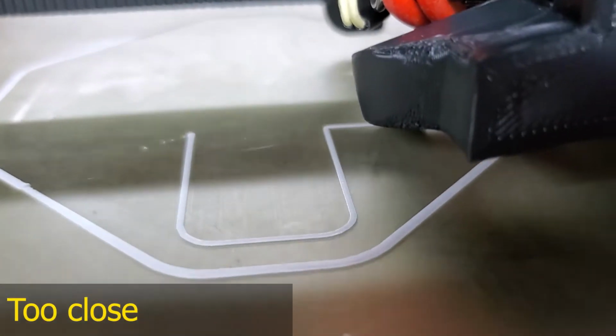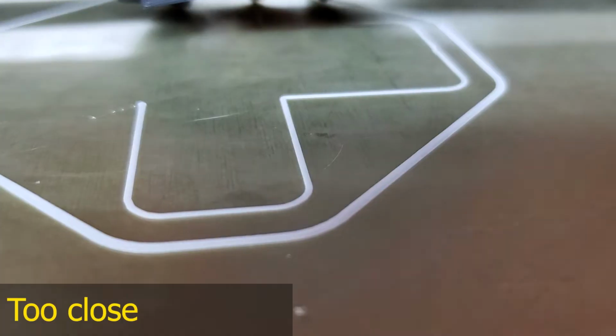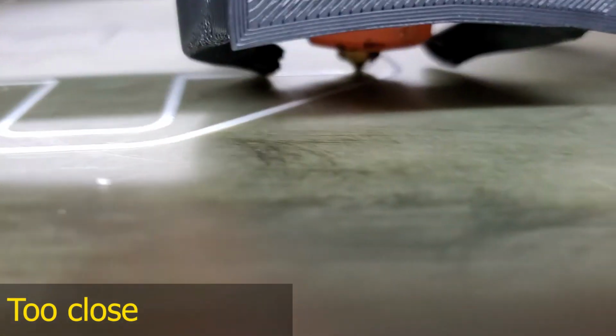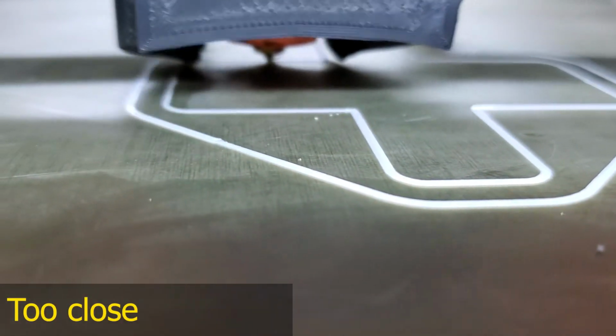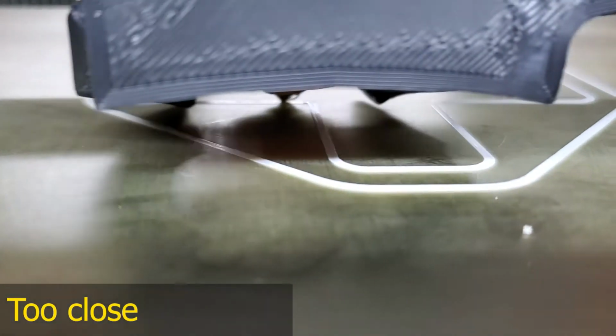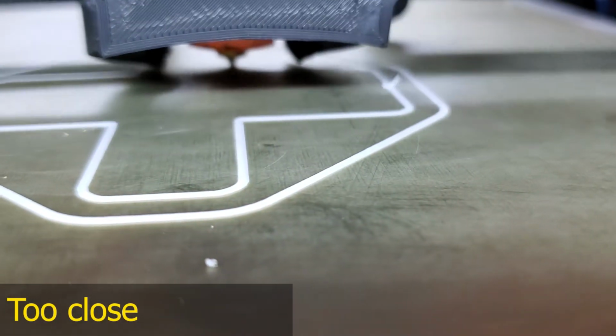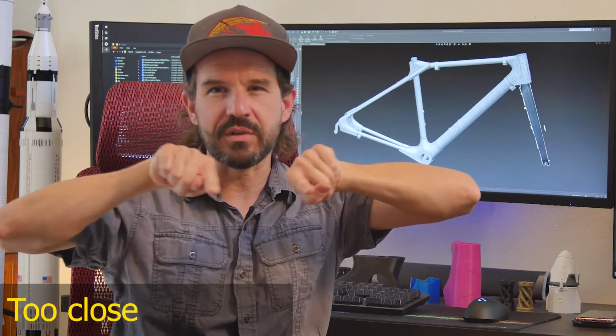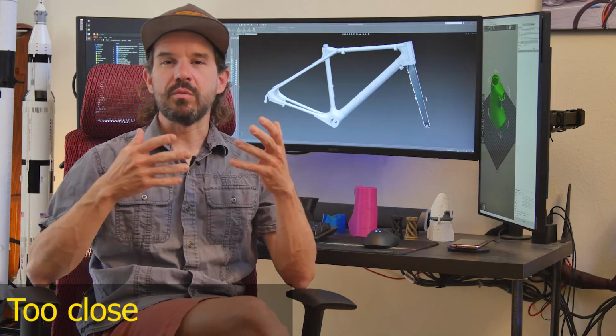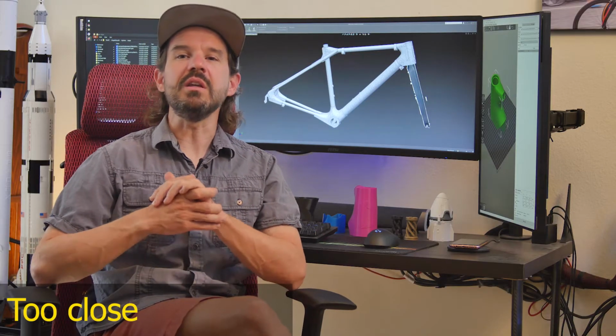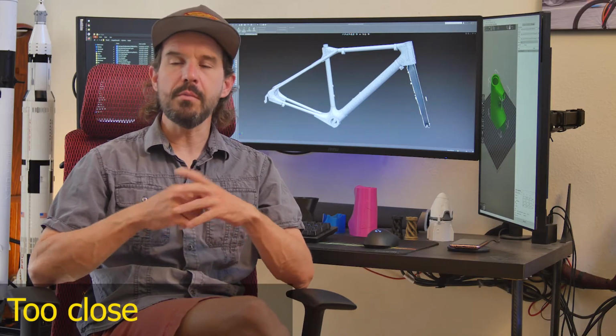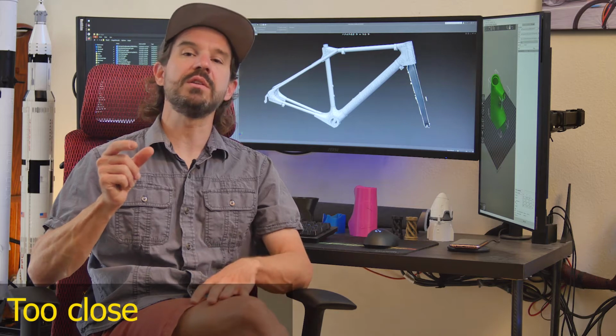In the next example, we can see filament coming out, but your Z offset is still way too close. The cross-sectional shape of the extruded filament will have a very flat top, and the line of filament extruded will be much wider than the nozzle, as there's nowhere for the molten plastic to go but out the sides. This will cause rather distinctive patterns if you're using a skirt or a brim or just a lot of perimeter lines in the first layer.